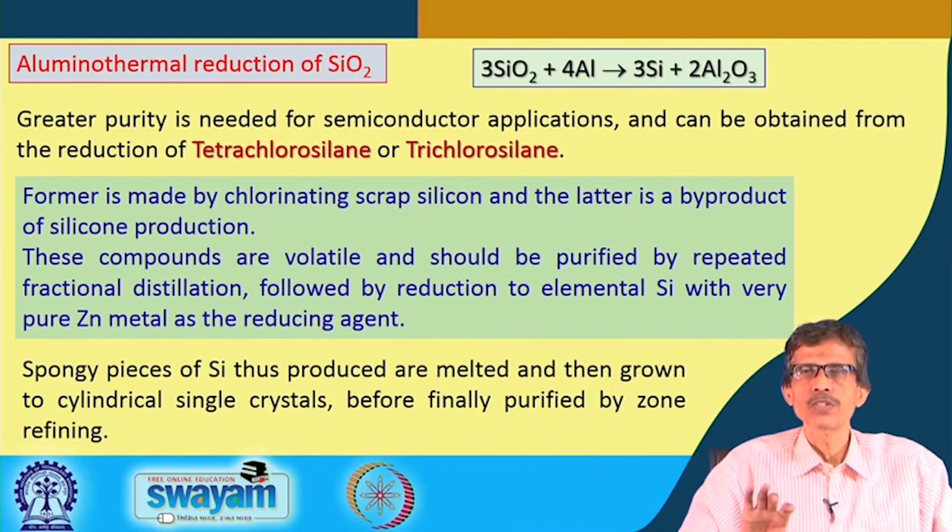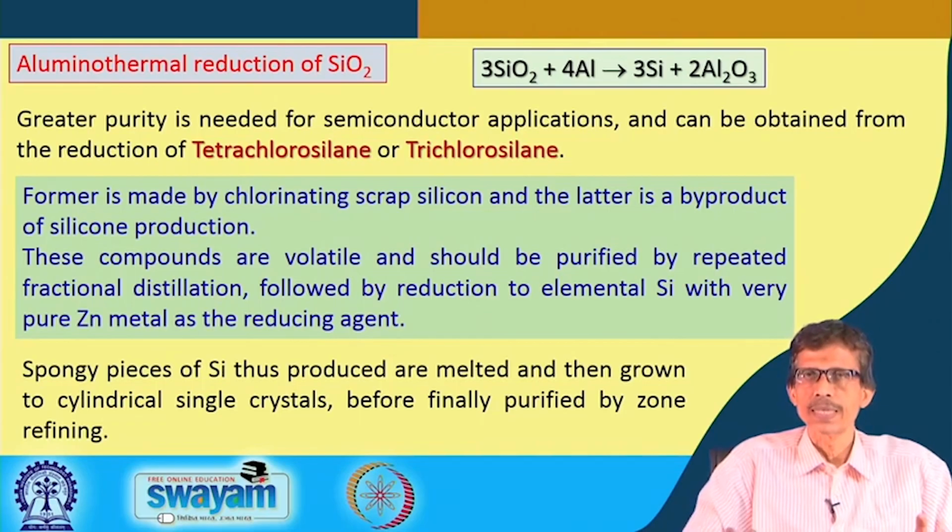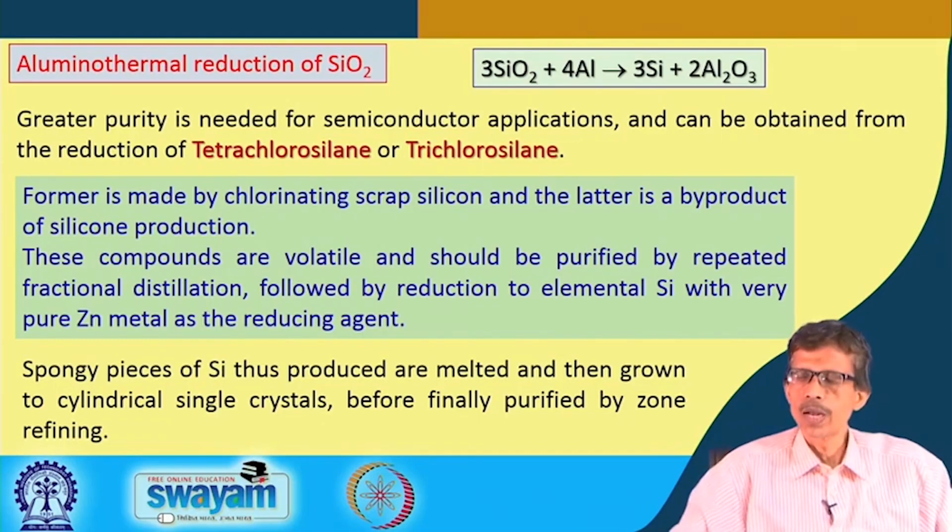Ultimately, the whole range of impurities are moving from one part to the other, and the concentration of the impurities is getting accumulated on the right hand side, and on the left hand side the purity is increasing. So, once it is reaching over there, we do not rely on further movement; we reach there and cut that particular part, because all the impurities present in the entire rod have been accumulated in this small part, and the rest is now utilized for making more and more silicon.